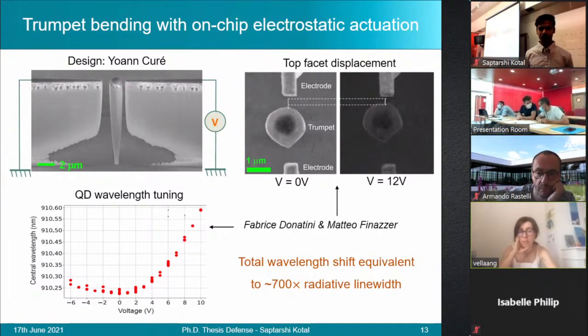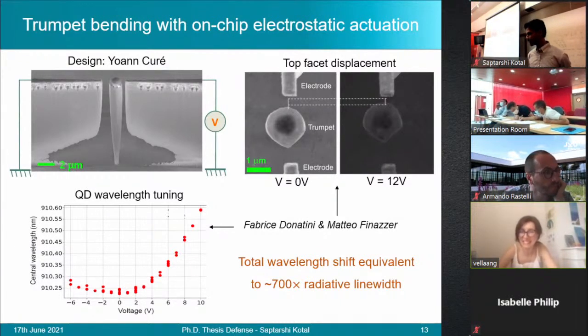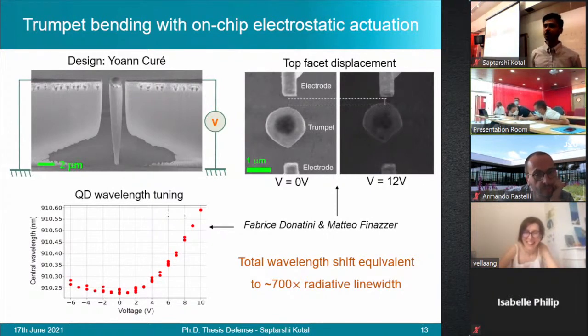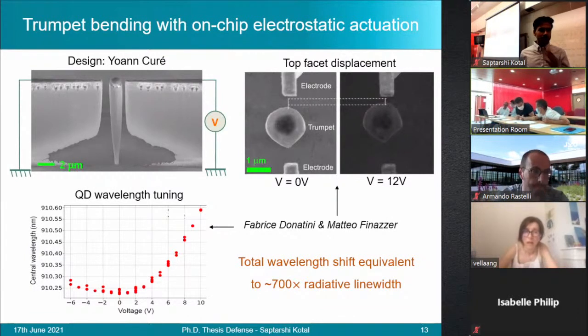Yes, but for negative voltages, you don't have results from the simulations. So maybe it would be interesting to check. By looking at this, we are thinking that maybe there's some sort of residual negative doping on the device itself. So when we apply a negative bias, instead of attracting it, it ends up pushing it back a bit. To be honest, we have not gone much further than that.